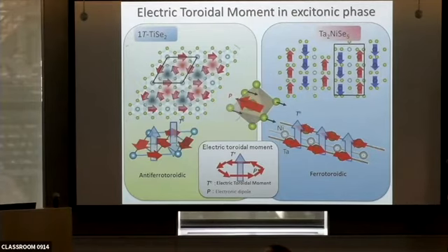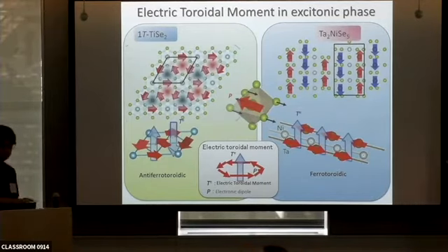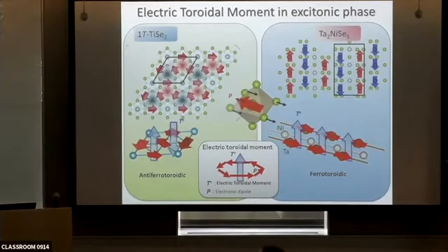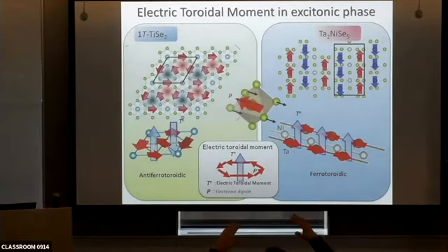The discussion we had yesterday with this linear Raman: if you compare selenide versus sulfide, the 2 terahertz mode is completely different in the selenide. The whole behavior is different. There is a huge spectral weight change, and all these little modes are coming up beneath 2 terahertz, changing the spectral weight. It looks like a super broadening of this mode. But if you look at your experimental data, it looks quite normal, the alpha and beta modes in the experiment.